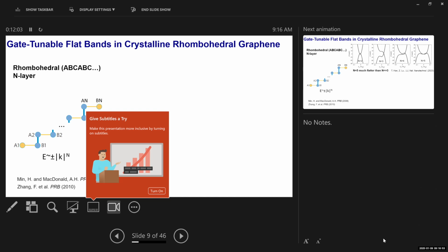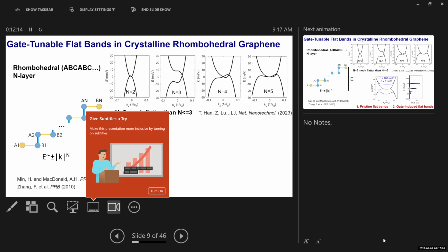If you've got monolayer graphene, this gives you the famous linear Dirac cone, huge Fermi velocity, nothing to do with flat band. But you can tune up the layer number N here, and very quickly, when you get to something like 4 or 5 layers, you've got flat band for free, okay?